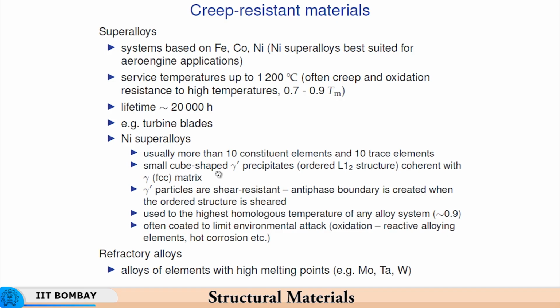So, small cube shaped gamma dash particles coherent with the gamma FCC matrix. So, these are the ones which are present, and they are there to reduce the creep rate. Now, these precipitates again will be effective only when you have power law creep present in the material, because these gamma dash particles are shear resistant, and they are used to the highest homologous temperature of any alloy system, that is of the order of 0.9.